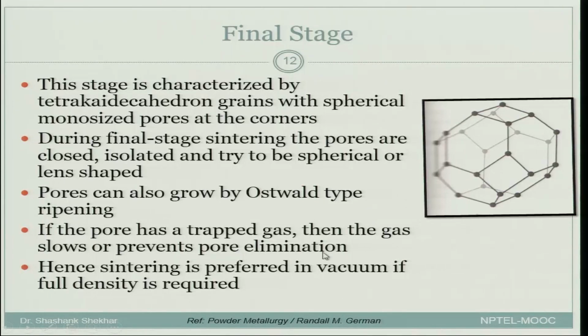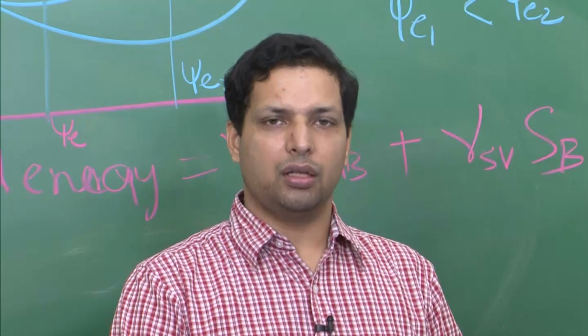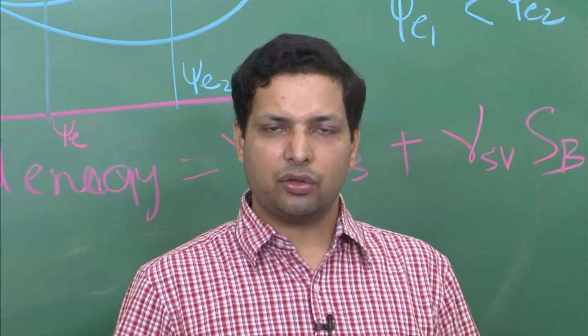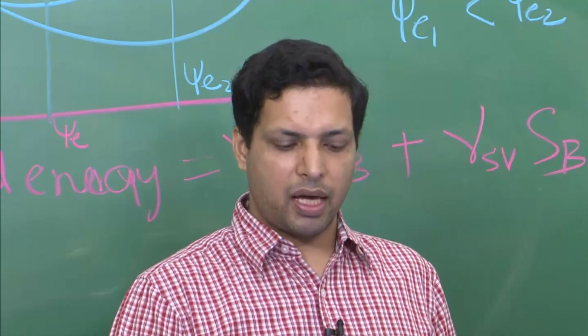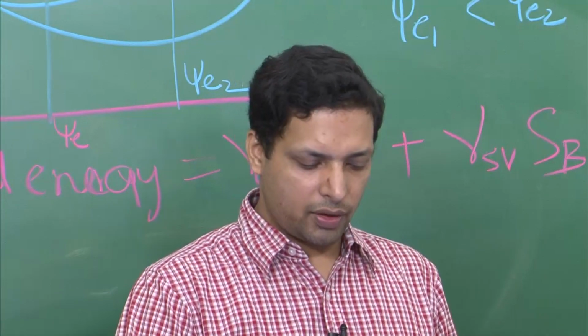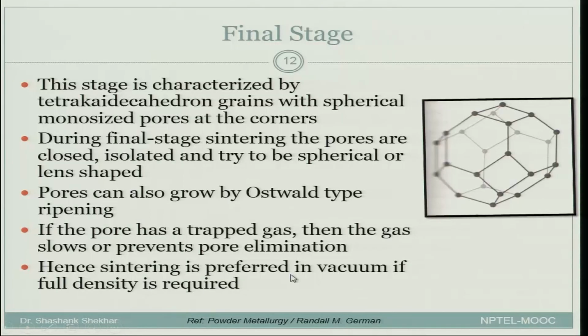Then the gas slows or prevents pore elimination. Now, if that gas is remaining there, it will not escape. Now, it is closed, it is isolated. No matter how much pressure you apply, you cannot get rid of those gases. Hence, sintering is preferred in vacuum. If you want to get a very high density, get rid of all the pores, then you have to do the sintering in vacuum.